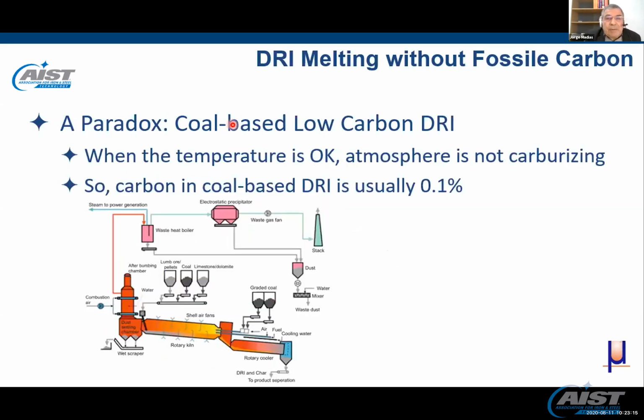I will go back to old times, as I am the oldest speaker here, and to the paradox of coal-based low-carbon DRI. When we worked with the kiln to make sponge iron based on coal, what we got was low-carbon DRI. 0.1 was normal, because when the temperature is okay in that kiln for carburizing, the atmosphere is not okay. And then the opposite situation. When the atmosphere is okay, the temperature is not good for carburizing. So we usually get low carbon in there.